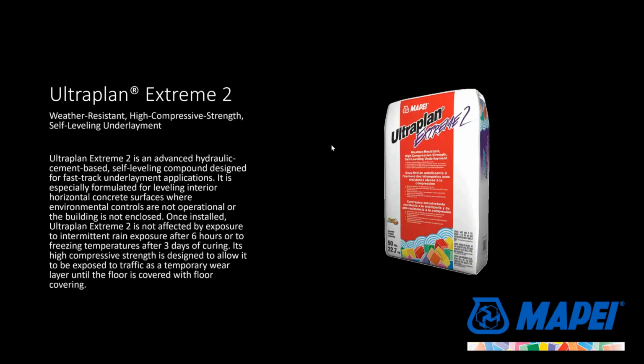Ultraplan Extreme 2, as I mentioned at the beginning of this discussion, is our go-to product solution. It's designed to be used in environments where there's no windows, no doors, could be exposed to the natural environment, rain, snow, etc. It can be exposed to rain within 6 hours after application and not show any signs of degradation. Same thing about freezing conditions. Give it 3 days to cure, and you can allow it to freeze and it won't be a problem. Now that might be a problem for some of our other products, and that's why Extreme 2 has its home.